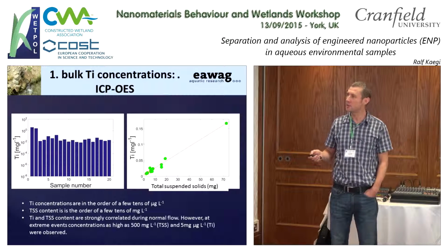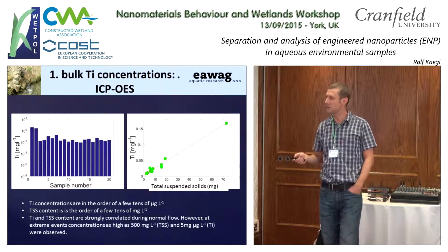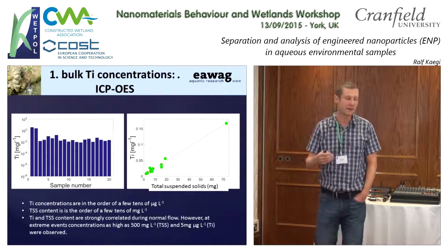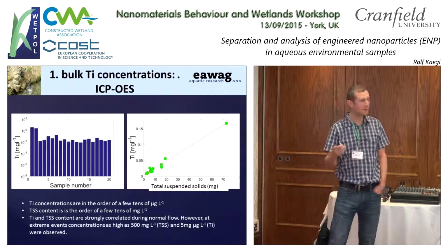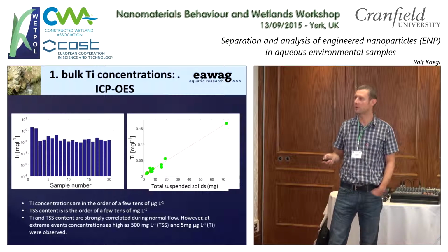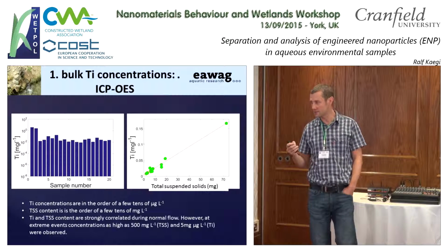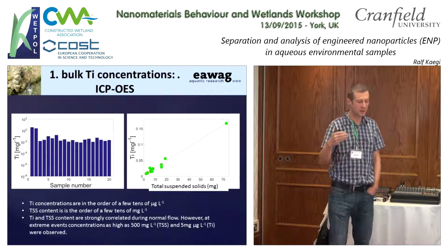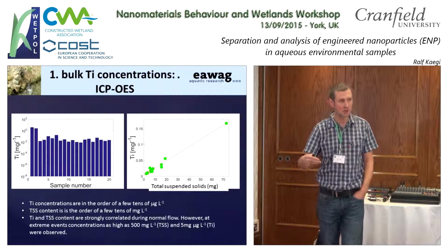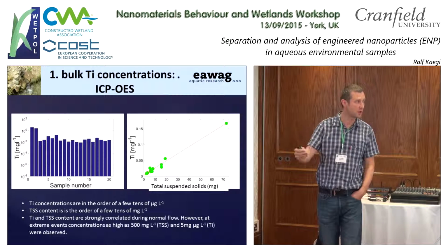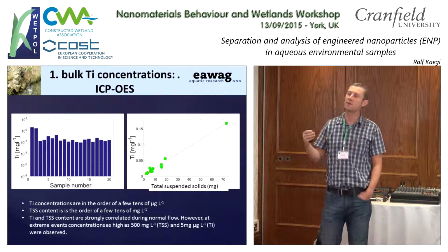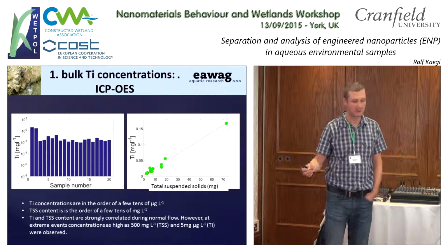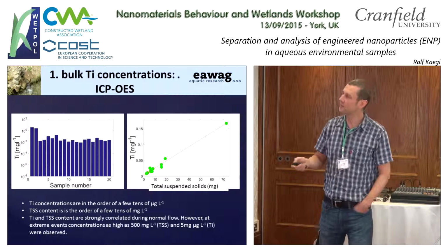The interesting thing is now, if you correlate the total suspended solids with the titanium concentration, you see this nice linear correlation. That means, based on a turbidity measurement, which reflects the total suspended solids, you can possibly assess the titanium concentration, and if we can convert it to a number concentration, we may eventually assess the flux of nanomaterials coming out from a landfill. Now, this is the bulk concentration.